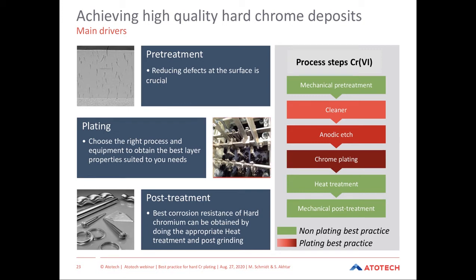Typically the substrate must be in a very good quality. So the grinding or the mechanical pretreatment operations have to produce a defect and sliver-free surface. In the plating section, of course, the right process for the kind of equipment or for the requirements of the final layer has to be chosen.